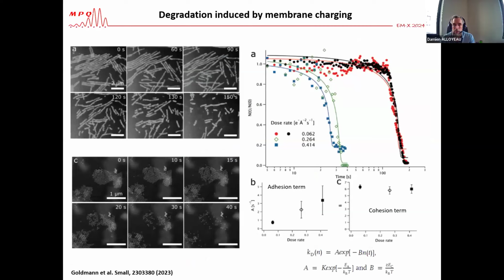And we have studied the degradation kinetics of those nano objects through the electron beam. And you see that over time, you have a loss of the crystallinity of the supercrystals. And they all have the kinetics of degradation is always the same. First, you have a plateau, and then a drastic drop in the number of nanoparticles that you have inside your nanocrystals. And we fit those curves with a kinetic model that accounts for the desorption of the